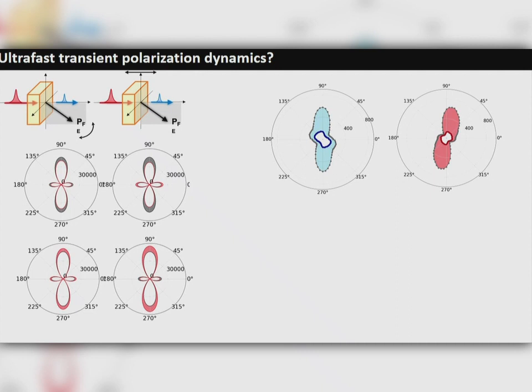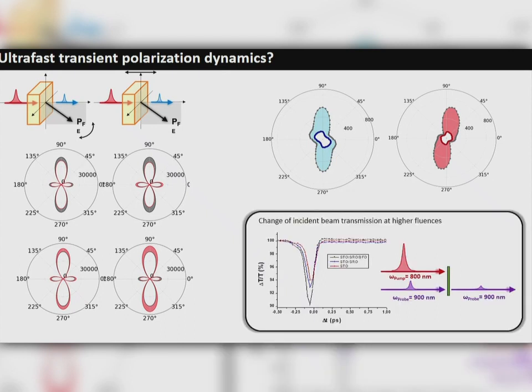And as we can see here, around T0, you have a huge change in this asymmetry, which points out that we certainly have a huge electric field generated perpendicular to the layer. Of course, we did some checks also, because as we are shining quite a large amount of light, I forgot to say it's about 40 millijoules per square centimeter, we have checked the change in transmission, because we are going through the whole structure. It's about 10%. So of course it plays a role, but it cannot explain all that we have seen here, especially the change in the angular dependence.